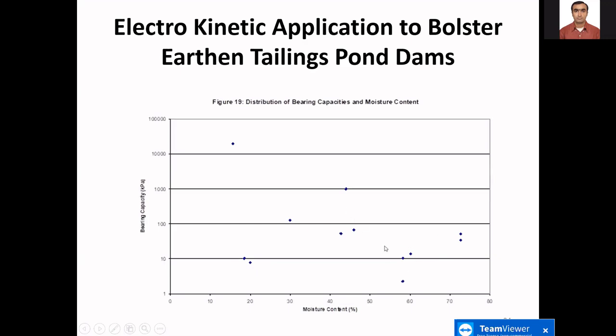So there are 12 samples that we took here. Of those 12 samples, 10 passed the 10 kPa test, and only 2 did not, and that's an achievement of 83.3% of the goal, even though we were really focused on the goal. Part of the testing to look at further feasibility would be to determine how much control we truly have